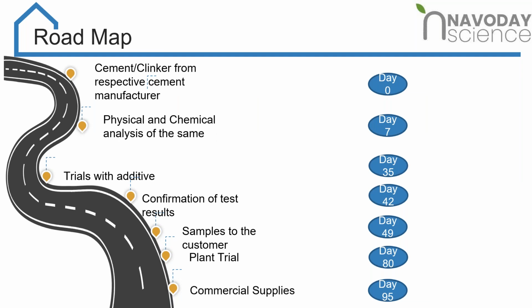So the roadmap we normally follow with any cement plant is, once we receive the cement or clinker from the respective cement manufacturers, we analyze it for its physical and chemical properties, and find out how much alumina is there, what the basicity and acidity are. Then we do trials with different types of additives, and formulate the additives that are suitable for that particular cement or clinker. What I'm trying to say is that this is not one solution that fits all. Novomax is different for each cement manufacturer, and the same sample is sent for the plant trial and then the commercial supplies. Next slide, madam. Thank you.